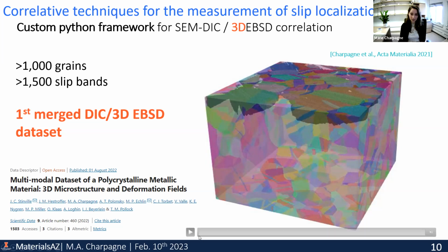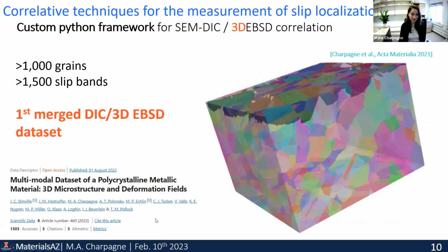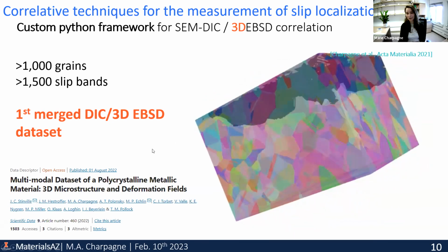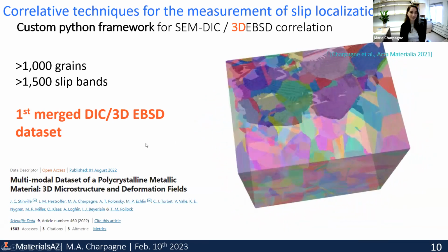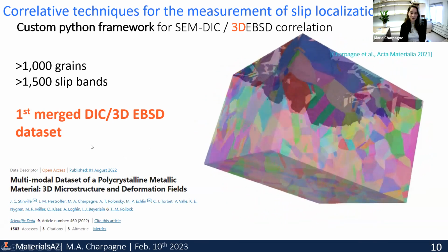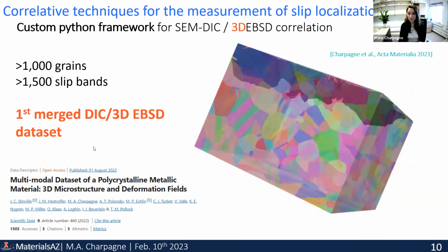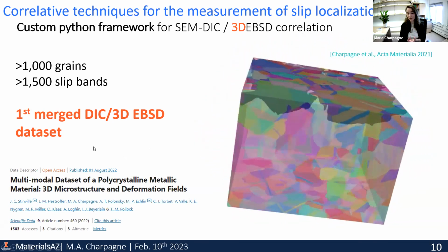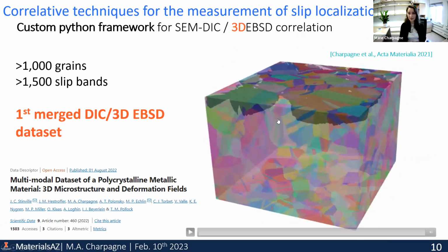And this is very much COVID work here. I want to mention, we're all complaining about the COVID, but if COVID didn't happen, I would never have done that. So I came up with this framework that was even more ambitious, where we can reconstruct slip bands in 3 dimensions. So here, using the tool I just introduced a couple slides ago, where we can recombine EBSD and DIC, I extended this framework so that we can combine DIC with not 2D, but 3D EBSD.